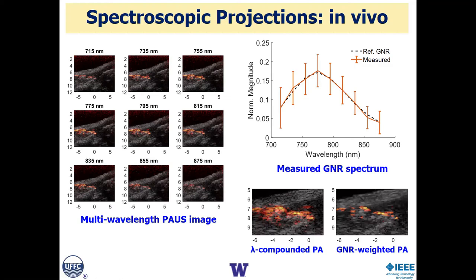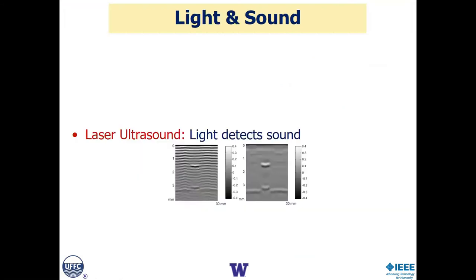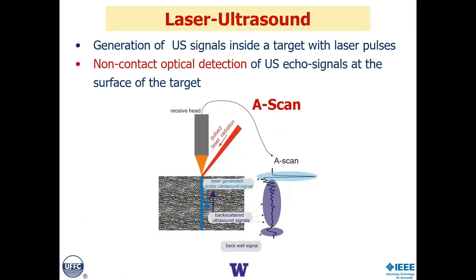Okay, that's the first part as we focus on. We'll now go to the second, where light is used to detect sound. And this is something you all are very familiar with, because I'll use the rubric of laser ultrasound here to introduce this. In laser ultrasound, we use the photoacoustic principle, but here the light does not penetrate the object; it simply illuminates the surface of an object where it is completely absorbed within micron-scale thickness at the surface, which then efficiently launches a longitudinal ultrasound wave perpendicular to the surface.